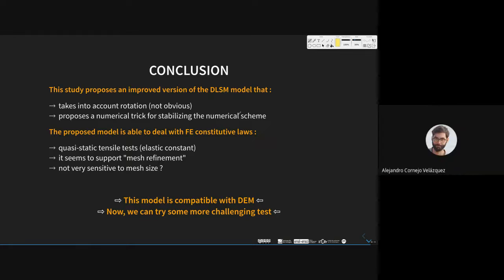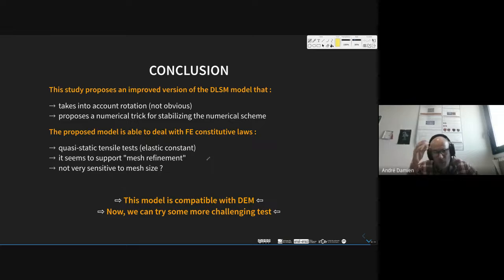And actually, the plasticity and damage that you're using normalize the fracture energy available over the finite element size. Yes. This is one way of normalizing for the different meshes that you're using. It is not perfect. I think that those differences can be expected somehow, the ones that you're experiencing in the last example. I would expect that with the FEM, but maybe I'm wrong. I don't talk about this point because I'm not really mastering it, but I put an internal length depending on the Voronoi size.